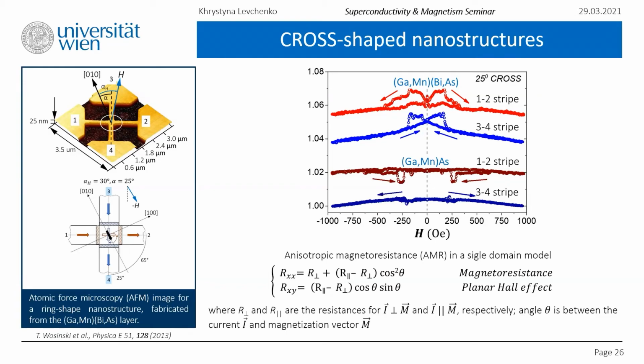Let us look at this. On the left-hand side, we see the AFM image of the nanocross. So there are 4 contact pads denoted with numbers, and there are the crystallographic axes along 0, 1, 0, and some angle alpha, which denotes along which direction the magnetic field was applied. So the general idea in this case was to create an imbalance between resistance responses along the two stripes. The current is flowing along them, and the resistance response is generated because of the different angles of the magnetocrystalline easy axis in the middle segment of the nanocross in comparison to the stripes.